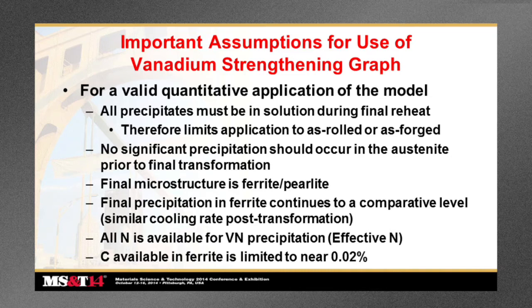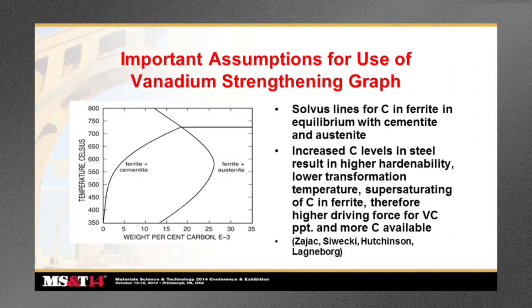Final precipitation in ferrite continues to a comparative level. In other words, the processing should be very similar, and then the similar cooling rate after the transformation has completed. And all nitrogen that you presume to be part of this model is in fact effective nitrogen. That is, it is available for vanadium nitrogen precipitation. Carbon availability in ferrite is generally limited to 0.02%, but we will talk about an example where it may be higher than that. This, in fact, is that example.